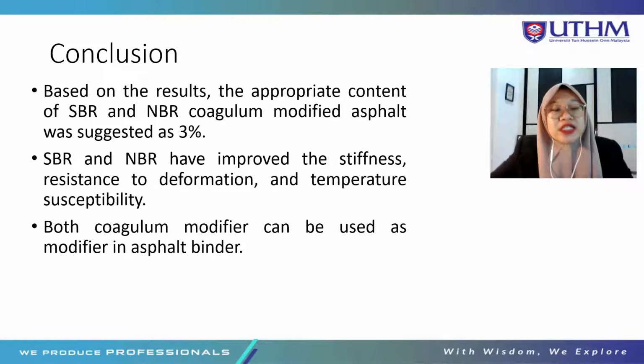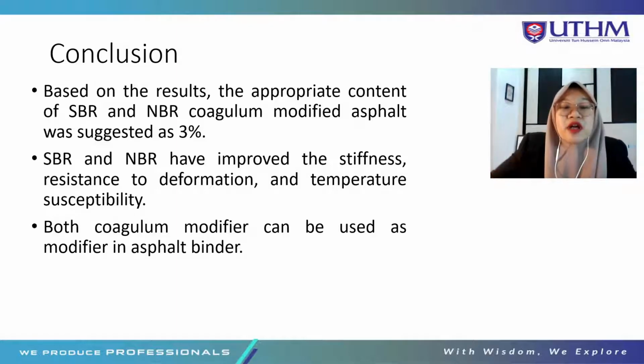So the conclusion is that, based on the results obtained, the appropriate content of SBR and NBR coagulum modified asphalt is suggested as 3%, and the SBR and NBR have improved stiffness, resistance to deformation, and temperature susceptibility. Both coagulum modifiers can be used as modifiers in asphalt binder.